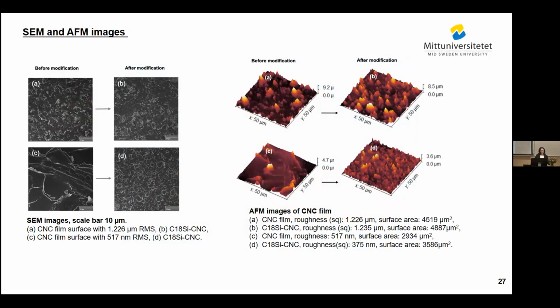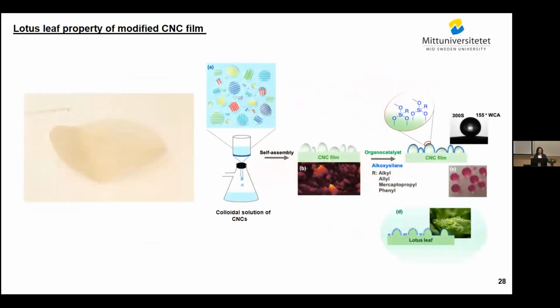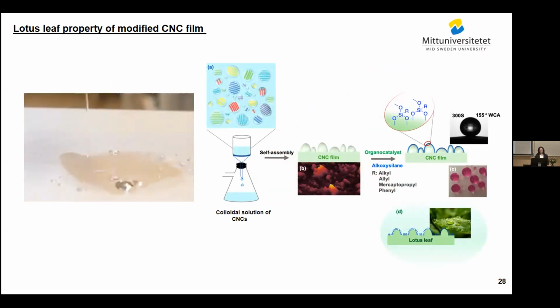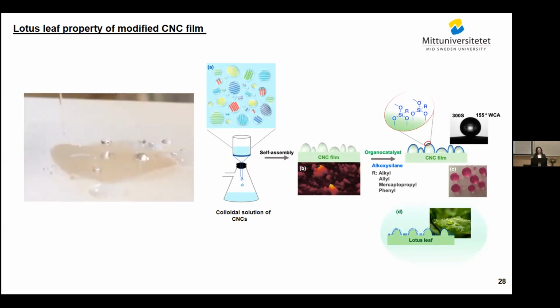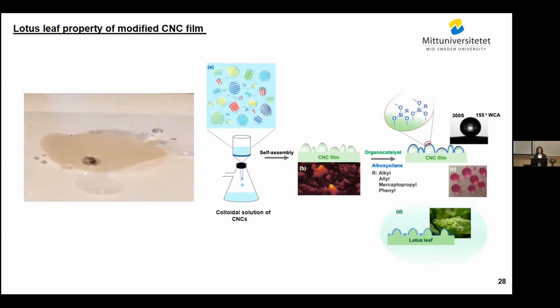The SEM and AFM images show that on both smooth and rough surfaces, we have an even and homogeneous distribution of the chemical. But what makes the difference is the roughness of the starting material. I recorded a video here, hope it works. Yes, this is the CNC I prepared in the lab. It means that with the filtration system, this self-assembly and roughness, followed by alkoxysilane modification in the presence of an organocatalyst, I could prepare CNC films that show properties like a lotus leaf.